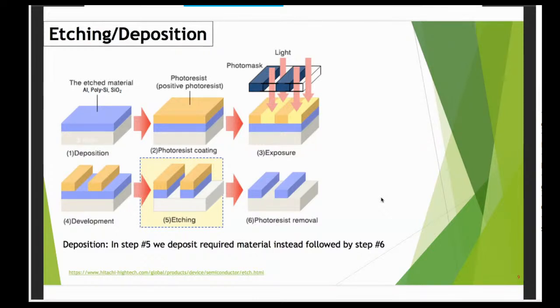But you can also use dry etching in the form of a plasma. So what you do, you take it into a vacuum chamber, you excite the gas inside, most likely a noble gas like argon, or if you want to introduce some chemistry into it, you can introduce chlorine or oxygen into the chamber, and then you apply a large electric field across the gas, and the gas will become ionized. It will create ions that will then bombard the structure and etch away the material.